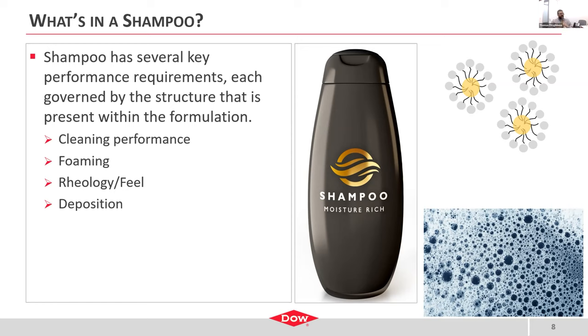The first and probably most important is the cleaning performance. If you think about, well, how does a soap clean? You can look at the top right there where I have some cartoon drawing of some micelles. A lot of the material inside of this shampoo are surfactant systems. So these are amphiphilic systems that have a hydrophobic tail and a hydrophilic head group. If you put them on a greasy surface or oily surface, they can solubilize the oil inside of these droplets in the form of a microemulsion, and then be washed away, giving you good cleaning performance.